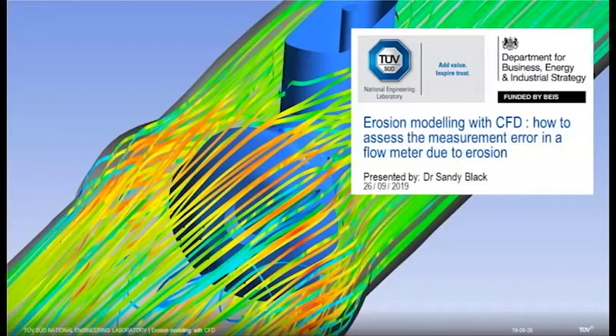So, for example, each time you double the velocity, I think the erosion potential increases roughly by about 6 times, and you might typically get 30, 40, 50 meters a second. That's not uncommon. So even small amounts of sand can eat away at the pipe walls. So other things you could do as well is try not to have any blind tees. Perhaps have some 90-degree elbows, which are long radius rather than short radius.